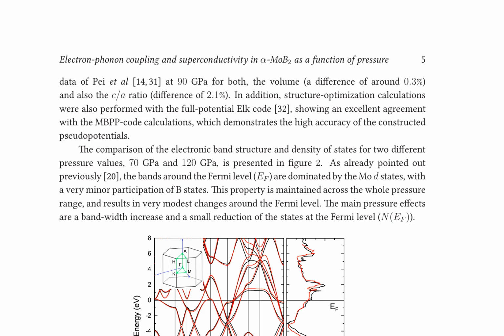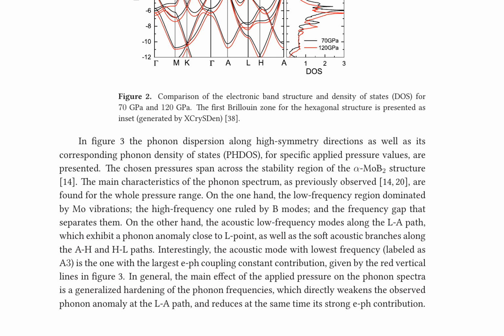A comparison of electronic band structures and density of states at 70 gigapascals and 120 gigapascals, as shown in Figure 2, reveals modest changes around the Fermi level with a bandwidth increase. The main pressure effects are an increase in bandwidth and a small reduction of states at the Fermi level.